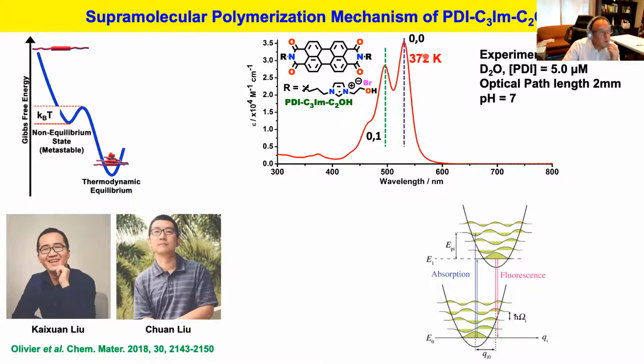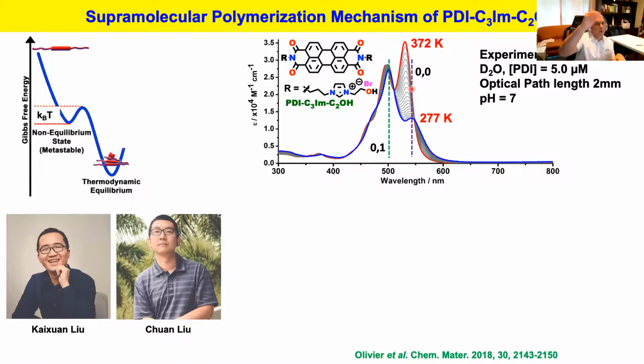How do we know that? We know that because we are using this spectroscopic fingerprint, the 0,0 vibronic transition and the 0,1 vibronic transition. And what is interesting, and that's one of the main reasons why we are using these chromophores, at least to validate the tools that I'm going to introduce you in a second, is that when I'm lowering the temperature close to 0 degrees Celsius, you can see this inversion of the 0,0 and 0,1 transitions, right? And what that tells us is that we go from molecularly dissolved building blocks into aggregated species.